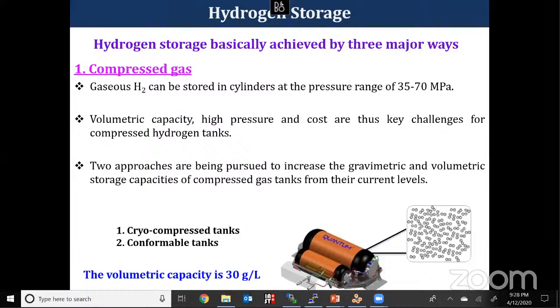One is a compressed hydrogen tank, another is a liquid hydrogen tank, and another is material-based hydrogen storage. Each method has its own advantages as well as disadvantages. In the compressed tank, we need a proper cylinder to store hydrogen molecules, and volumetric capacity is a major factor here. We get a volumetric capacity of 30 gram per liter, and we need a pressure of 35 to 70 megapascal.